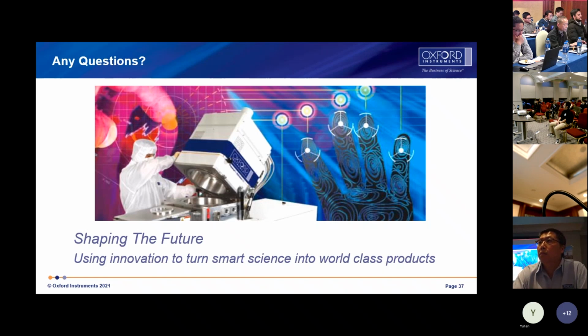So my question is, is that possible? I can just spin coat my sample with photoresist and pattern the design I need to do the low temperature ALD. Yeah, you can do that. You do the photoresist pattern and expose the area you want to deposit. Then you put the sample in the ALD chamber, do the deposition, and control the time to get the thickness. ALD is a very good conformal coating technique. So basically you can coat your nanowire and device. I don't know the material you use on the nanowire, but basically all materials are okay to coat by ALD film. But that depends on the thickness, because ALD is atomic layer deposition, so from the name you know the time is longer, because it does atomic layer by atomic layer. So a few nanometers thickness would be okay.